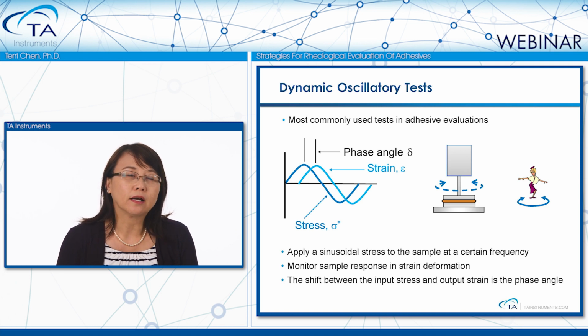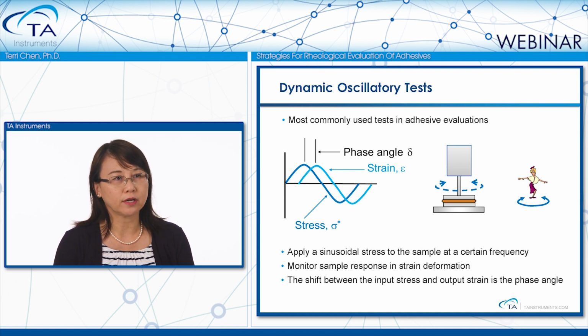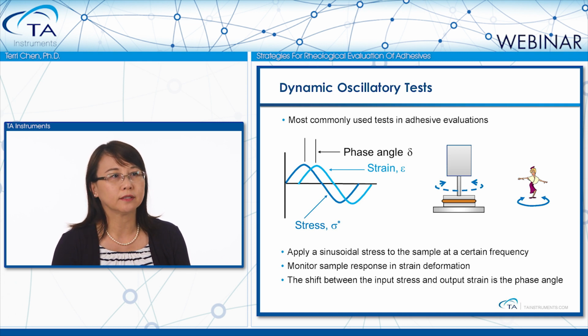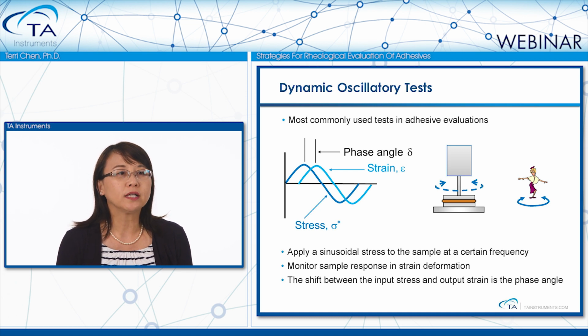Dynamic oscillatory tests are the most commonly used rheological test in adhesive evaluations. In an oscillatory test, a sinusoidal stress is applied to the sample with a certain frequency. The sample response in deformation is monitored and recorded. If the input stress is within the linear viscoelastic region of the material, then the output strain should also be in a sinusoidal waveform. The shift between the input stress and the output strain is the phase angle, which is used to describe the viscoelasticity property of the material.